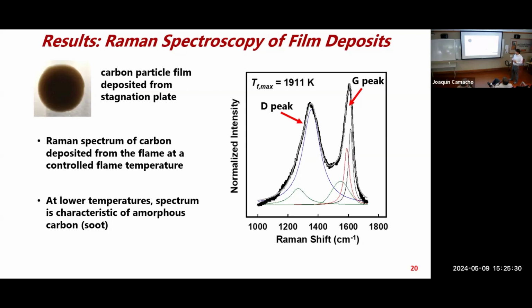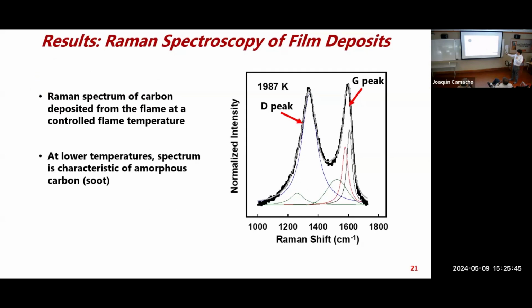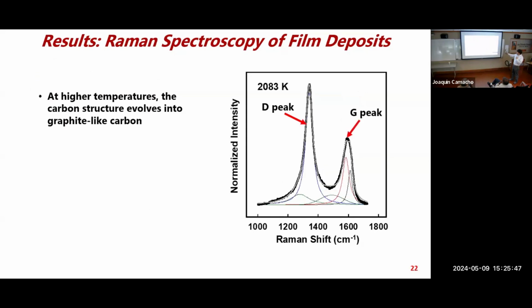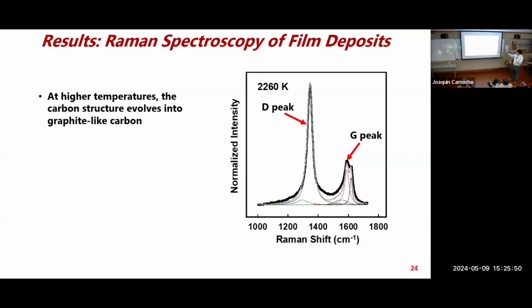I won't present that there, but the overall structure, the signature, looks like soot formation. But interestingly, as we keep the equivalence ratio the same and increase the temperatures of these flames and look at these films, what we get is an evolution where at higher temperatures, the Raman signature changes. As a matter of fact, this is not soot anymore in terms of the Raman spectra of the film.